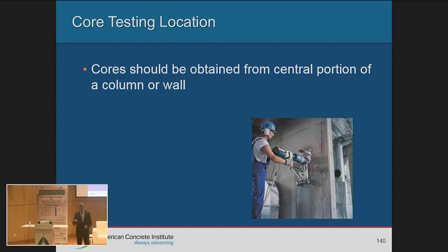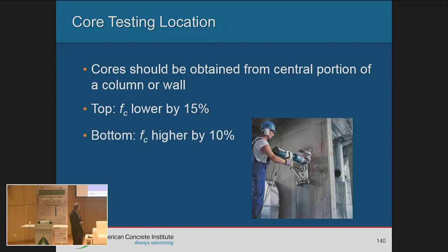Any volunteers? In the middle. Why? And why not? The middle is right. Correct. Middle is correct. No, actually, what they found, again, is that if you take it at the top, your concrete strength is about 15% lower. Okay? If you take it at the bottom, your concrete strength is about 10% higher.